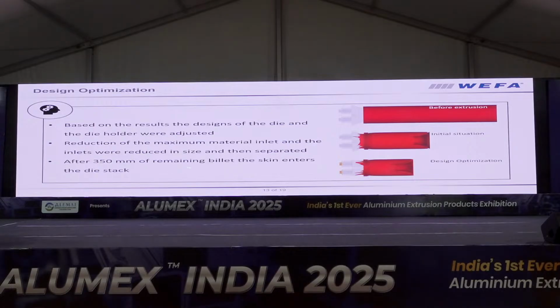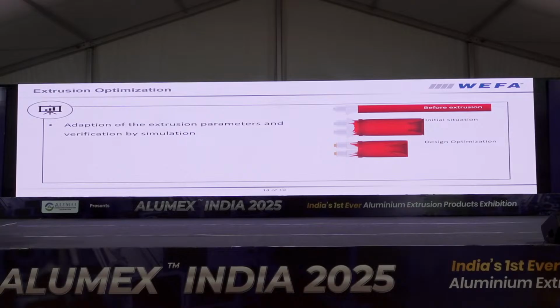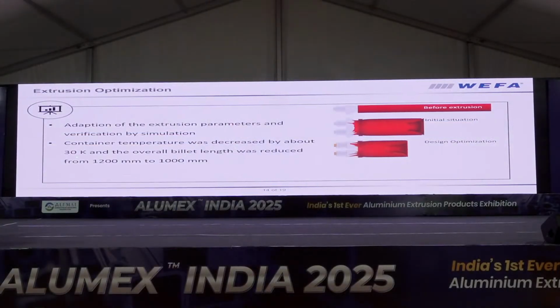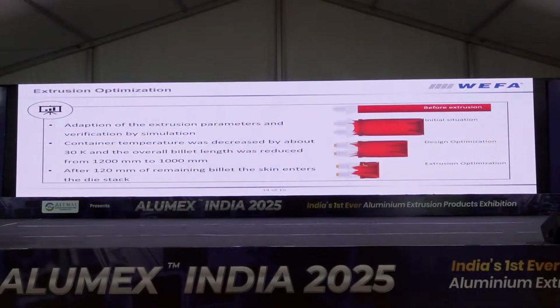After 350 millimeter, the butt length was even still long, with 350 still too long. So we were also forced to do something during extrusion, to work with the extruder. So what did we do? We adapted extrusion parameters. What did help is that we decreased the container temperature, the overall container, not only part of it, so also the entire container temperature, reduced it by 30 kelvins, and we also reduced the billet length by 200 millimeter. What happened is that we see only 120 millimeters left for creating the skin entering into the die stack. So tremendous success, also working together with extruders.